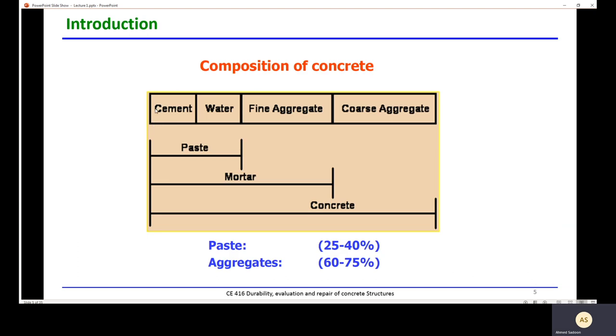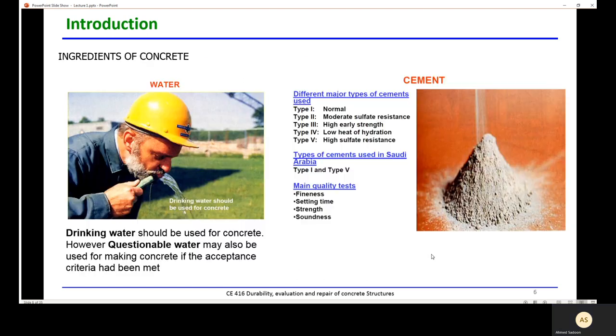If we combine cement with water we have paste; adding fine aggregate gives mortar; adding coarse aggregate gives concrete. The paste represents about 25–40% while the aggregate represents about 60–75%. Regarding water quality, if the water is drinkable it can be used for making concrete without question. For questionable water, criteria must be met — for example, compressive strength should be more than 90% compared with standard concrete.